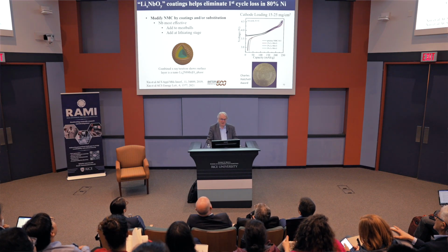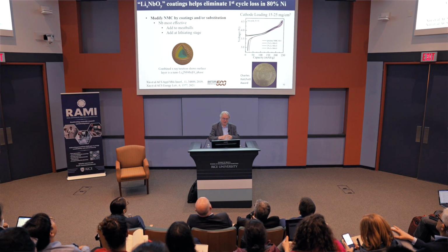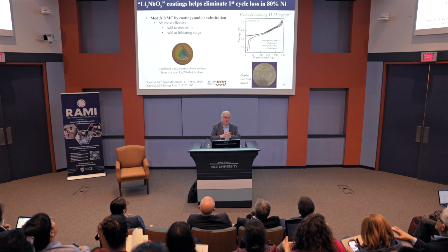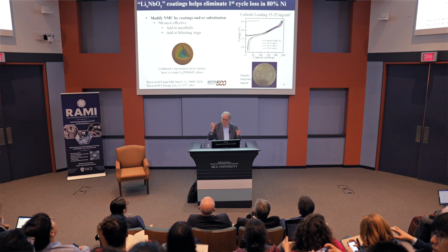And one thing we found out, modifying the surface of these materials does a lot to help, but modifying the bulk is even better. And I show you just some initial data we got with niobium. We looked at the whole range of these materials. We found niobium worked the best, partly because niobium is +5. It hangs onto those oxygens hard, so the oxygens can't easily move.